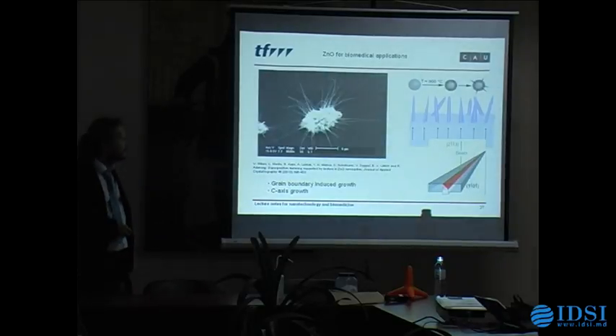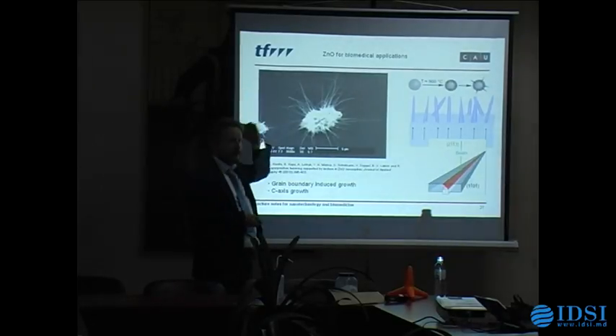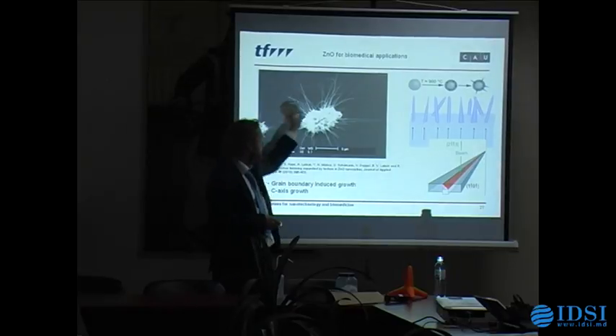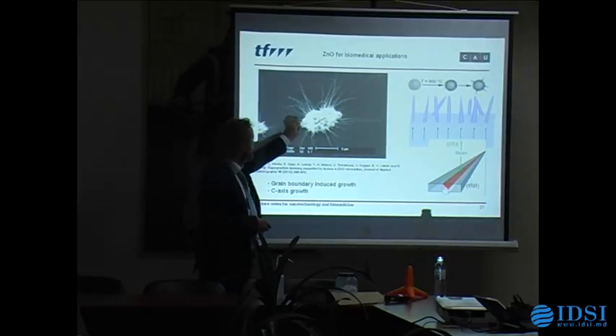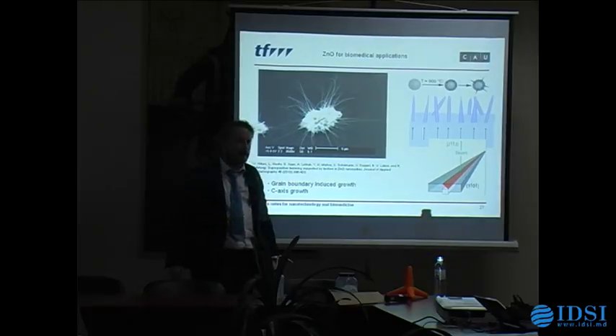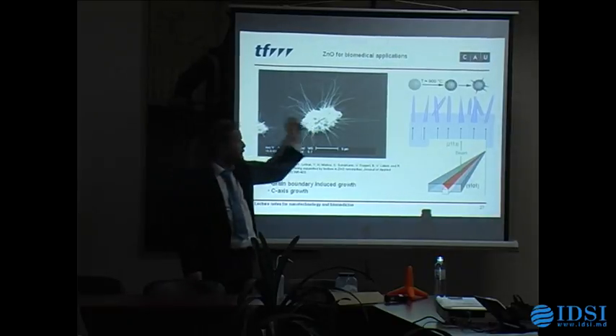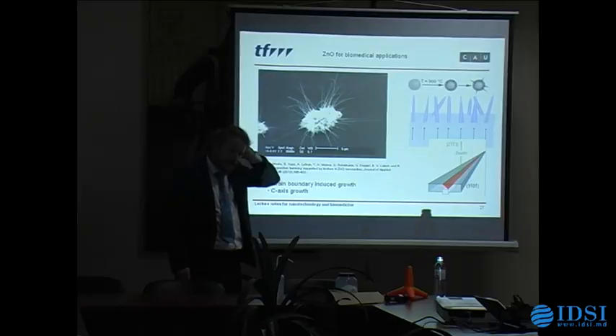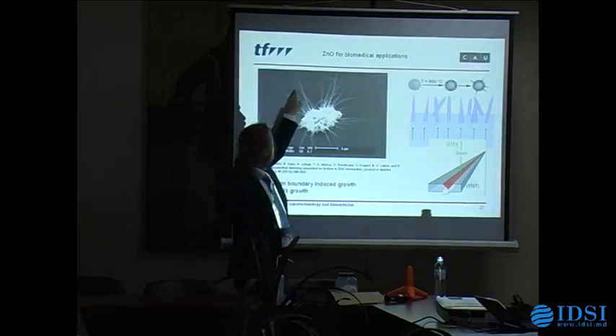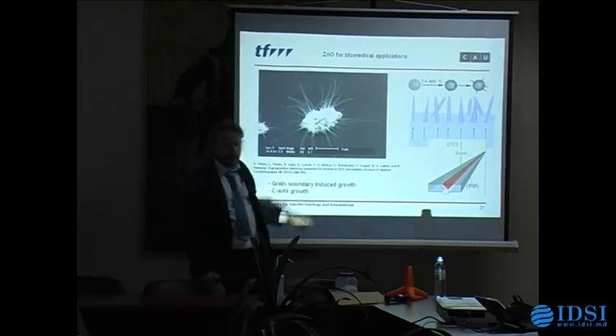And just if you take a zinc grain and oxidize it, more or less in a clever manner, you can put here some gold nanodots, for example, you have some growth of some little spikes which are going off. And these are still single crystal. And one funny effect, which has to do something with the size, nanoscale is different, is that those ones are curving around here. Why is that?